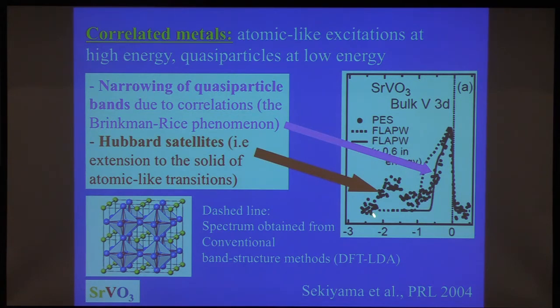But at high energy, there is a satellite peak, which is very simple to interpret in terms of an atomic transition. It's basically taking an electron out of this vanadium d shell and removing it. So it's an extremely simple atomic physics transition, which is a little bit broadened because we are in the solid state context.